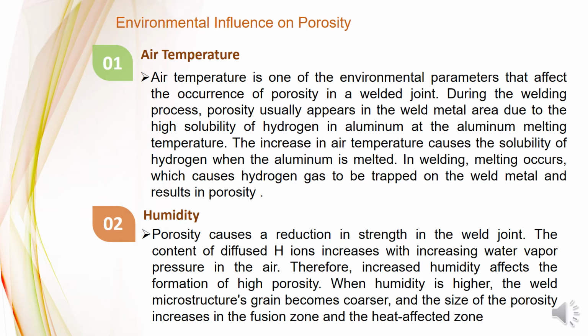Environmental influence on porosity. Number 1, air temperature. Air temperature is one of the environmental parameters that affect the occurrence of porosity in a weld joint. During the welding process, porosity usually appears in the weld metal area due to the high solubility of hydrogen in aluminum at the aluminum melting temperature. The increase in air temperature increases the solubility of hydrogen when the aluminum is melted. In welding, melting occurs, which causes hydrogen gas to be trapped in the weld metal and results in porosity.